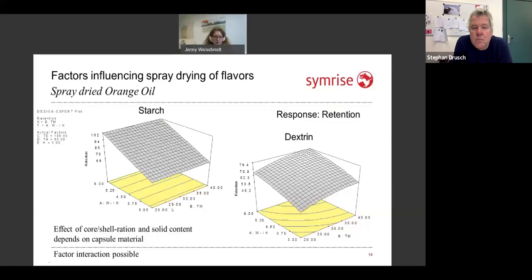Let's have a look at our orange oil in our starch and dextrin matrix. On one axis, I present here the ratio of core to wall material. 3 means 1 part active, 3 parts wall material, up to 1 part active, 6 parts wall material. You see, of course, the retention increases if you increase this ratio. The more material you have to entrap your active, the higher will be retention. The solid content, we've seen it before, doesn't have an influence at all.